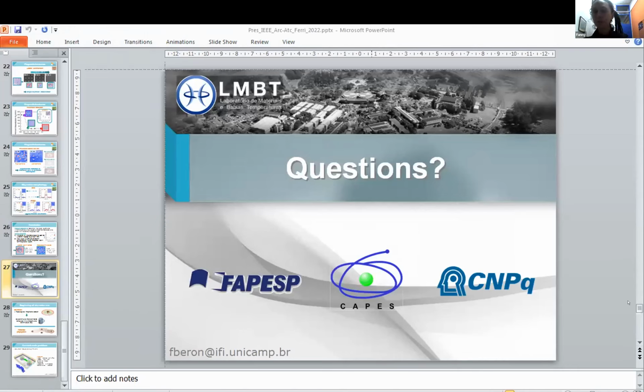First, we didn't perform XMCD at different fields, only at 1 Tesla. You need to apply a field that is strong enough to align your ferrimagnetic material without reaching the equivalent of the spin flop field, so you have the two sublattices in the same direction. Normally XMCD is made between 1,000 Oersted and 1 Tesla. You don't need to vary the field; you will not get any other information. So it's not a saturation that you have.